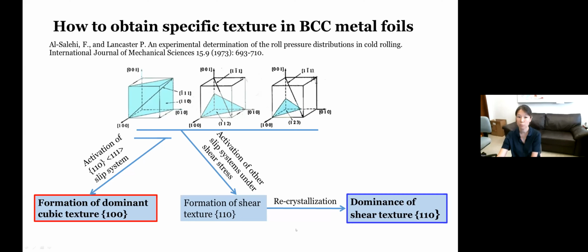So if you are able to initiate a recrystallization of the system, that will lead to the growth of the shear texture, that is the texture of 110 orientation, at the expense of the other grains of different texturings. And that will eventually lead to the dominance of the shear texture of 110. So that's the general theory.